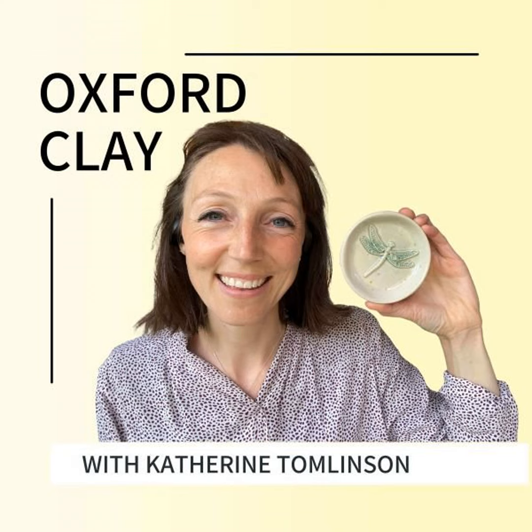I fire my work in the middle of that range, to 1,260 degrees, and that's the ideal temperature for the glaze I use, the ash glaze. It's a stoneware ash glaze. I use a stoneware clay that can withstand those temperatures and doesn't melt.